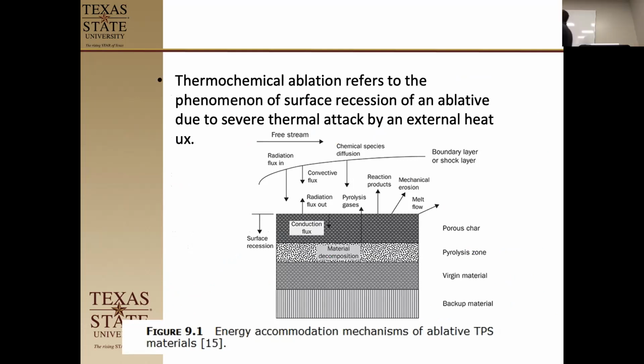Okay, so let's talk about what we call the thermochemical ablation. This is kind of what we were talking about before. You have your virgin material here that hasn't been heated by the heat flux. You have your stream coming out here. It's high heat, so you have radiated flux in. As it hits the first top layer, it decomposes and outgasses a little bit. And then the layer below it decomposes and outgasses. That puffs up the stuff. That's the char. And it puffs it up more. And so now that we have all this stuff that's decomposed completely, we have enough heat flux to continue to decompose and continue to outgas pyrolysis gases, which are small molecules and CO2, et cetera.